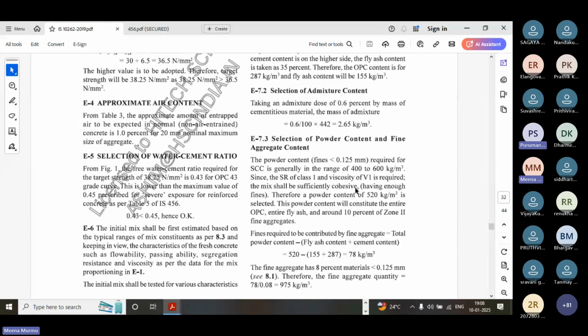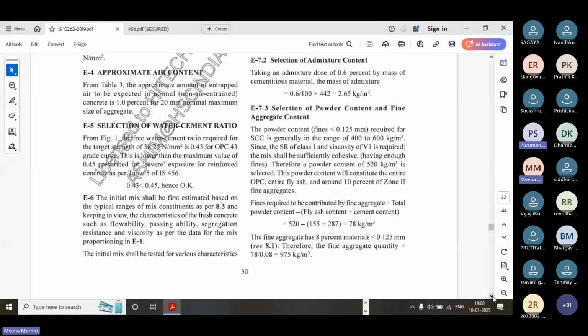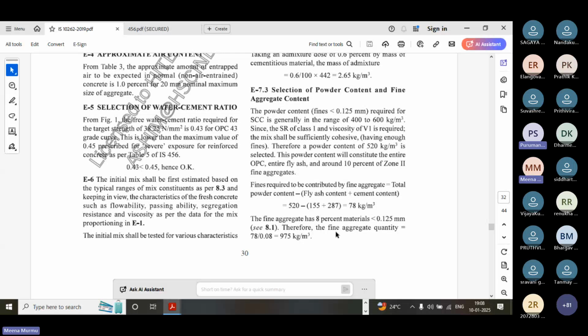For this, from where will we get our powder content? Powder content is 442. So 520 minus 442, we have to deduct. So this one is your 78 kg. That 78 kg will be collected from the fine aggregate. The fine aggregate has 8% material less than 0.125 mm, and therefore the fine aggregate quantity is 78 divided by 0.08, which is 975 kg per meter cube. Have you understood this, or shall I explain? Is it okay? Yes, ma'am. Okay, thank you.